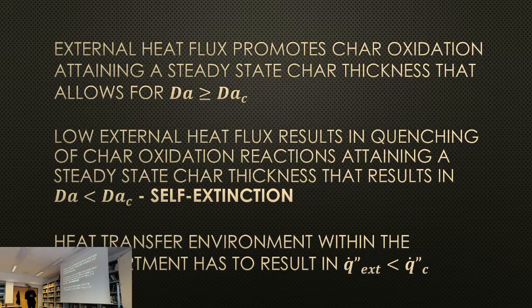So at the end, what is the criteria? The criteria is that an external heat flux promotes char oxidation, attaining a steady state char thickness that allows you to always have a Damköhler number greater than the critical Damköhler number. As soon as the external heat flux decreases, then basically char oxidation reactions stop, and then you get a Damköhler number that is less than the critical Damköhler number, and you get self-extinction. So the heat transfer environment within the compartment is the one that defines that external heat flux. So then you can convert these critical Damköhler numbers into a critical heat flux for self-extinction, and basically you evaluate the problem against that critical heat flux for self-extinction.